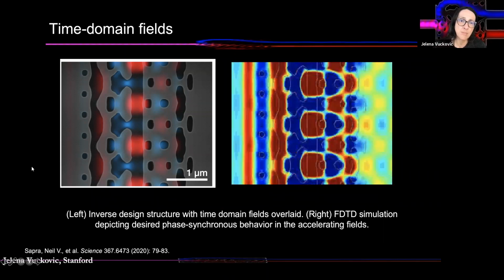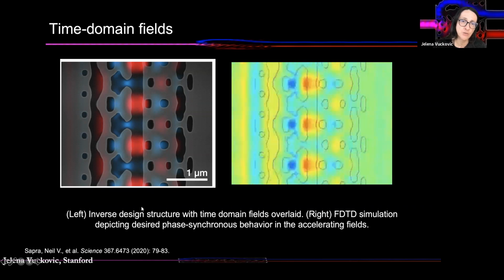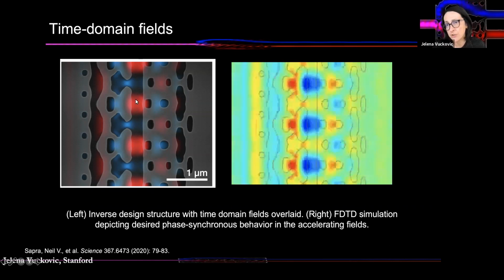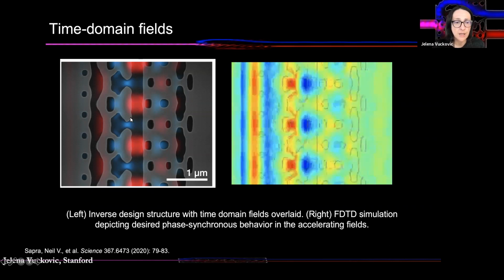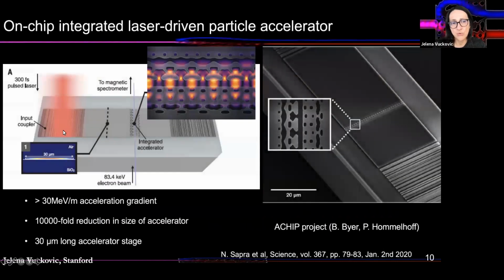And here is the fabricated structure. Again, this is a channel for the electron, and here you see the superimposed electromagnetic field, and this is in silicon. So then when you build the whole system, that's the stage, which is 30 micrometers long. This is the coupler for light. That light is coupled, guided here, goes to the stage of the accelerator, 30 microns long. And then here, the electron is coupled from the source. It has 83.4 kiloelectron volt energy. It's coming from a converted scanning electron microscope.